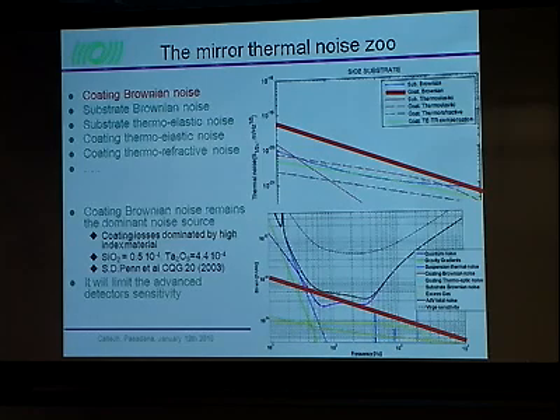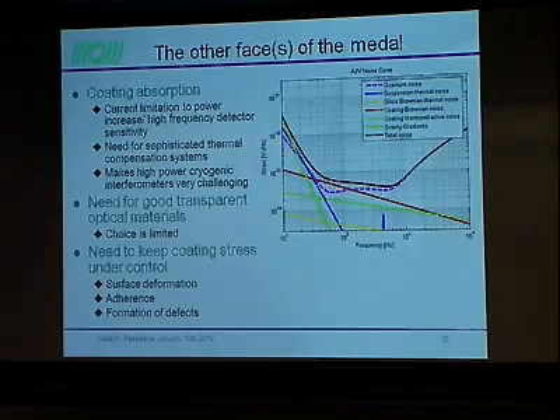One should keep in mind when doing these studies about coating materials that you cannot use whatever material you want, because you also want to have the coating absorption as low as possible. So people are asking to have 1 ppm, half ppm, 0.3 ppm, and so this is getting more and more difficult. And this is very important because in the end it will limit the sensitivity of the detector at high frequency. It determines how much power you can actually inject into the interferometer. So you need to have not only low losses in terms of mechanical losses, but also good transparent optical material, and the choice is limited there. There are other aspects that one should keep into account.